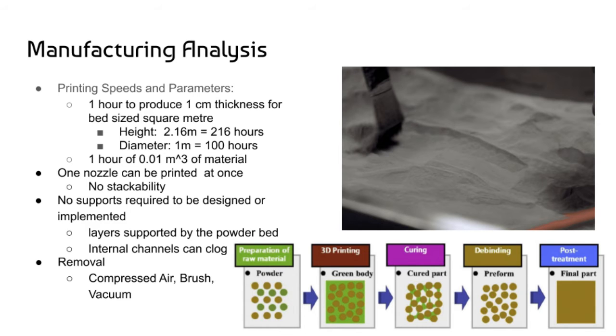Binder jetting has various steps that include preparation of the raw material, binder jetting itself, curing, debinding, and post-processing. Current limitations for manufacturing times include 1 hour for a bed-sized square meter to produce a 1 centimeter thickness, meaning a rocket of a height 2.16 meters can take roughly 216 hours, or if it's on its side with a diameter of 1 meter, it could take 100 hours to print.